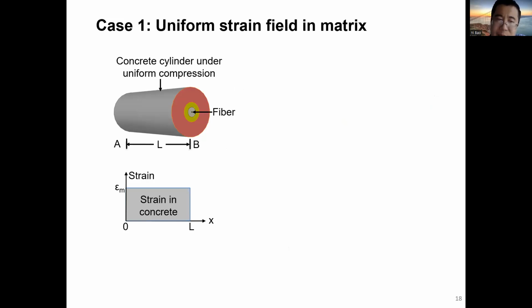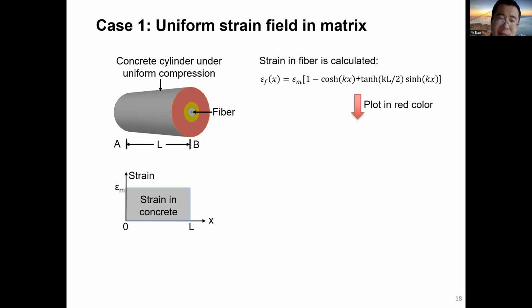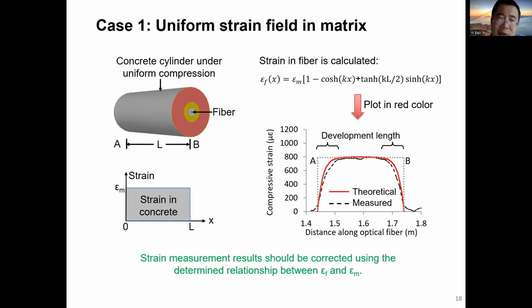This is very similar to the strain transfer problems for point sensors subjected to constant strain field. And in this case, we assume the fiber optic sensor is embedded in a uniform concrete cylinder. And if you apply uniform stress, like a compression to the cylinder, then we can easily solve this governing equation. And we generated the plots.